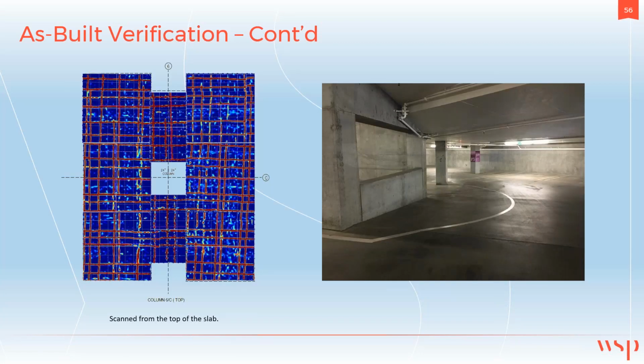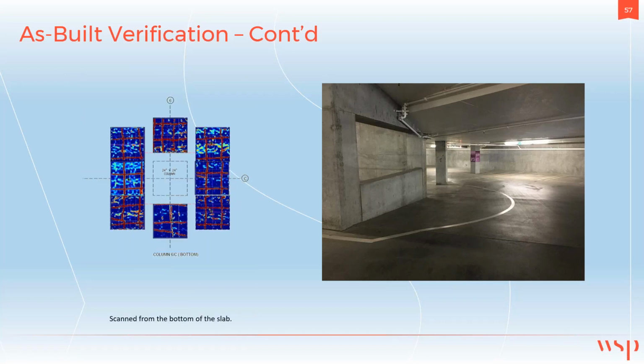Here are the results, showing our survey from the top. These are from 8 different individual surveys stitched together. This one shows the results when we surveyed the slab from the bottom. Mike mentioned earlier something about GPR frequency and penetration depth. The reason we had to survey both from the top and bottom was that the slab was 18 inches thick, but the depth of penetration for the GPR system we used was only 12 inches. So we had to test from both sides to entirely cover the full thickness of the slab.